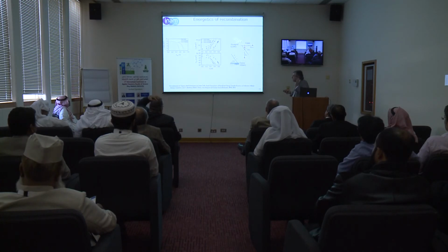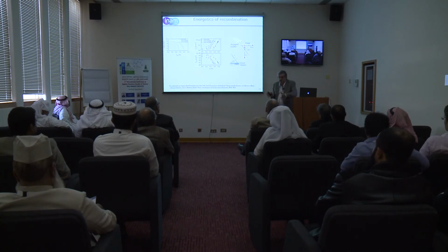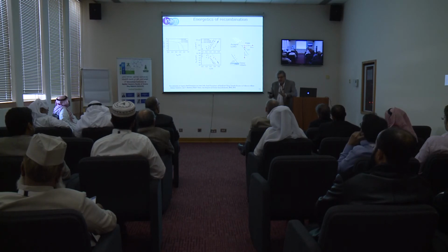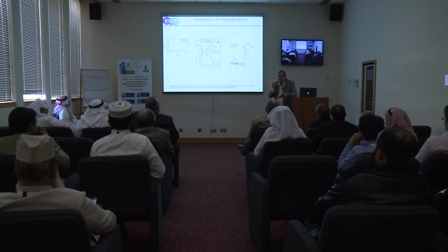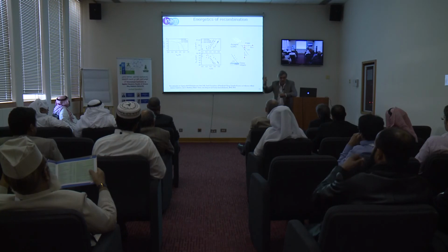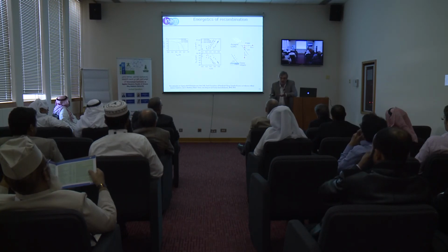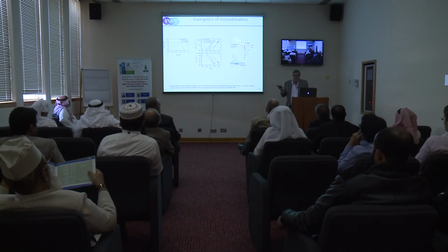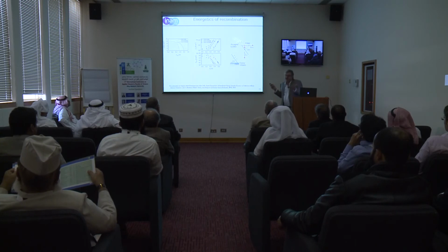Ideally we should do the same thing as here. In all solar cells we have this structure, and the perovskite must have the same structure. You have a lot of stories of contacts, etc., but in the end you are accumulating carriers, so you must have somewhere a big chemical capacitance. Then in parallel to this chemical capacitance you have a resistance, which is the loss of electrons, and that will be the recombination resistance. That will be the critical thing for the perovskite solar cell, but we didn't find it. We don't know where it is. So it's a big mess. The story I tell you today is not very nice, but this is the story I have at this moment.